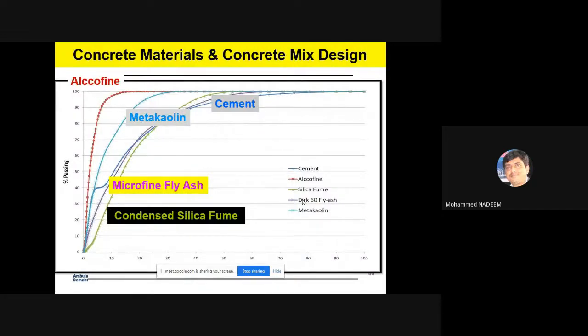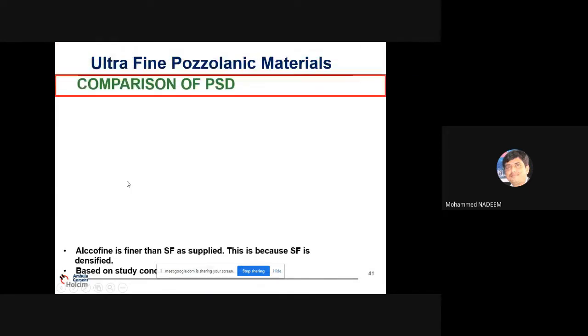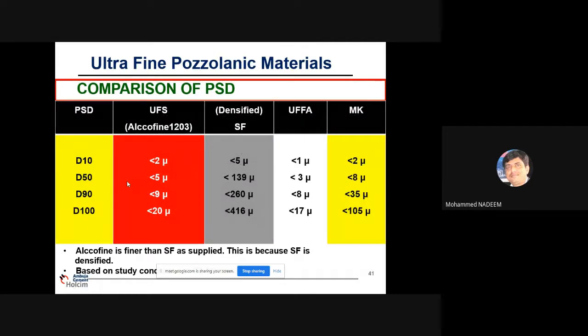And the PSD, particle size distribution, is explained here. This is our Alcofine, metakaolin, this is cement, microfine fly ash, and condensed silica. So very, very fine material, quite finer than cement. Particle size distribution is measured in the form of particle sizes. D10 means 10% of particles are of this size, D50, D90, D100. So these are the sizes, very fine material. If you see, D90 is 9 micron. In cement, D90 is around 75 or 80 micron. So quite fine.